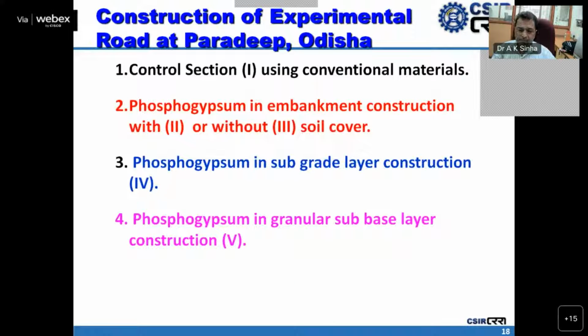Based on laboratory studies, a pilot study was carried out at Paradeep, Odisha. 5 sections were constructed using phosphogypsum. First one is the control section, which is constructed as usual using conventional soil and aggregate materials. The second and third were constructed using phosphogypsum as the only embankment material. Rest layers were constructed as usual, as conventional layers. The fourth section was carried out using phosphogypsum as a subgrade material. And in the fifth one, phosphogypsum as a replacement of aggregate in a granular subbase layer was used.